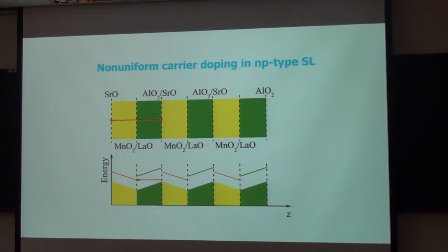The interesting phenomenon is the non-uniform carrier doping in the NP-type superlattice. For the system consisting of both N-type and P-type interfaces, we can find the electrostatic potential in the superlattice is a zigzag line. So there's charge transfer as long as the thickness of this polar layer is thick enough, making the charge transfer to the n-type interface.